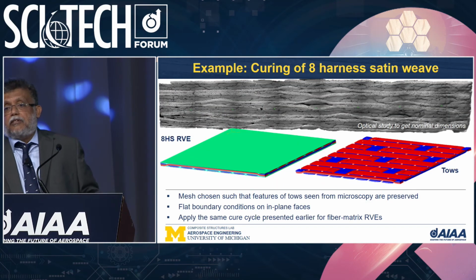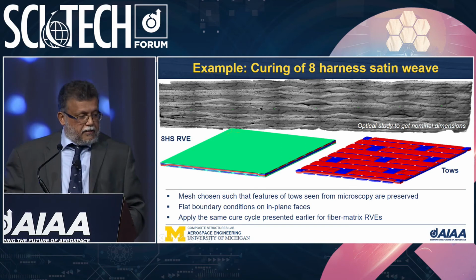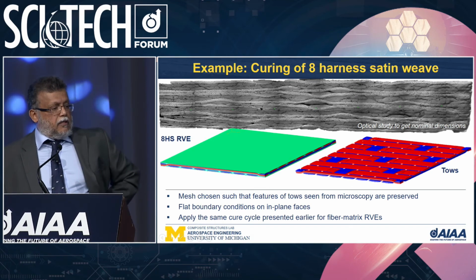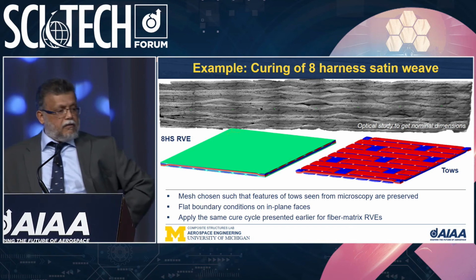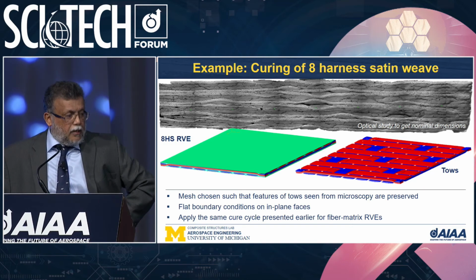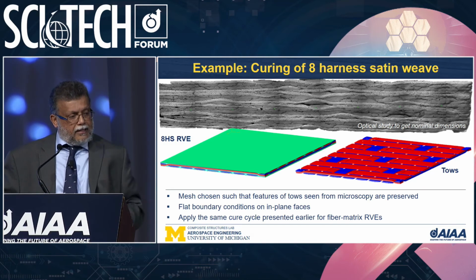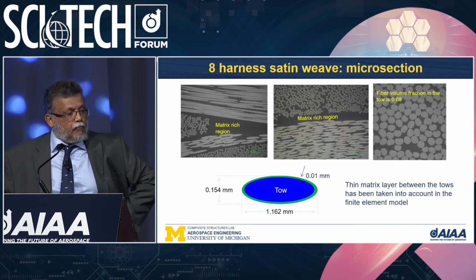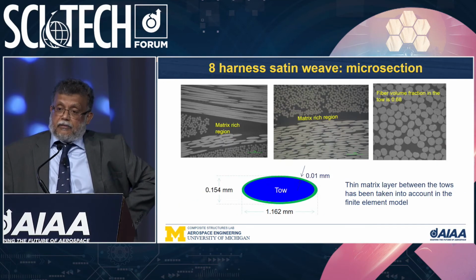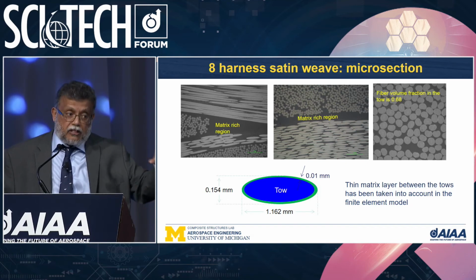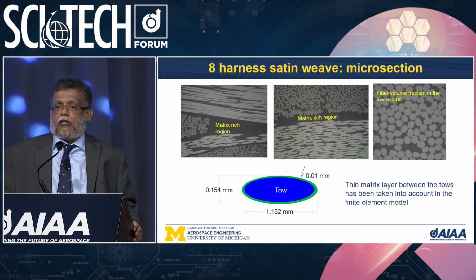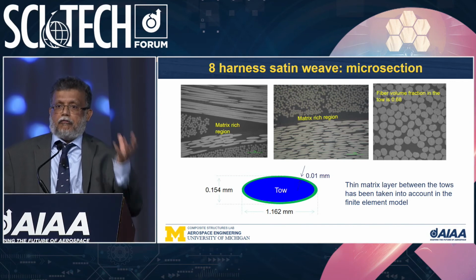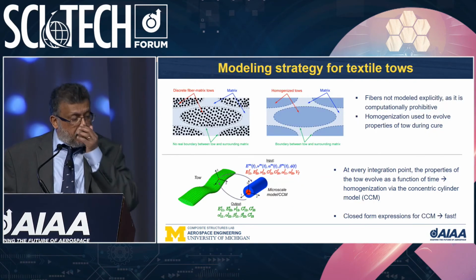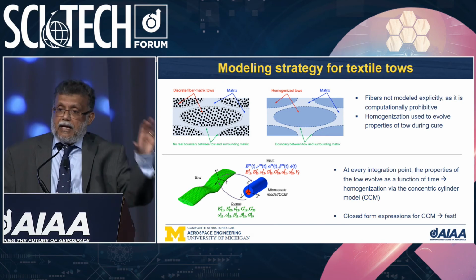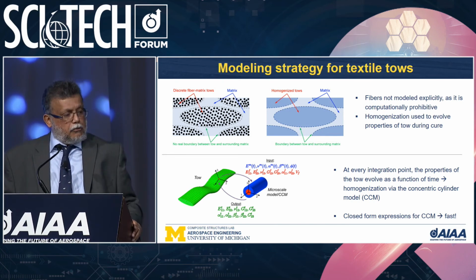I'm going to show you examples now of a project we did with GE, where we cured 8 harness satin weave textile composites at the micro level, where we made an 8 harness satin RVE. The RVE details are shown here. As I said, you cannot afford to model every single fiber at this level, so all the tows are modeled as homogenized evolving solids, and then you embed that in a matrix that's also evolving during the cure.